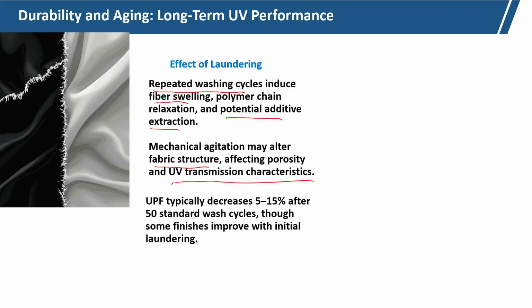The UPF typically decreases 5 to 15% after 50 standard wash cycles. That is experimental, it has been observed, though some finishes improve with the initial laundering.